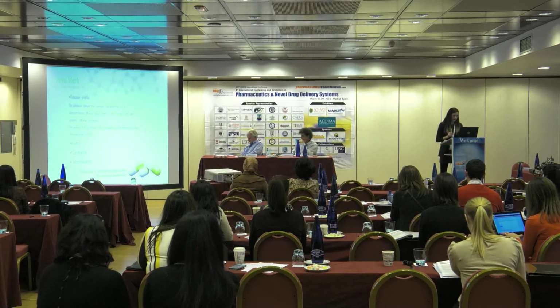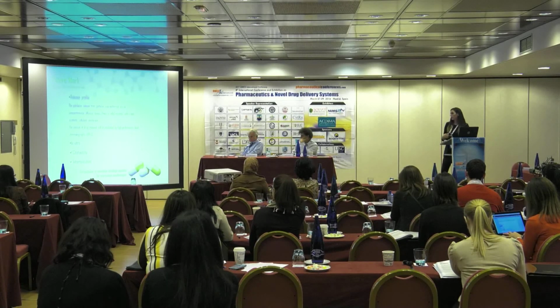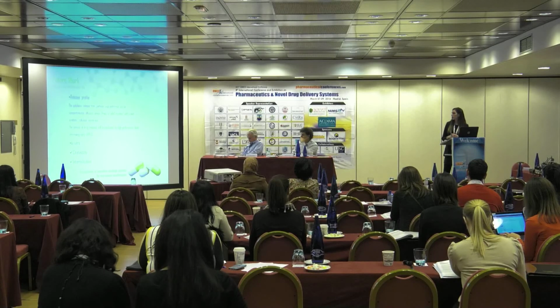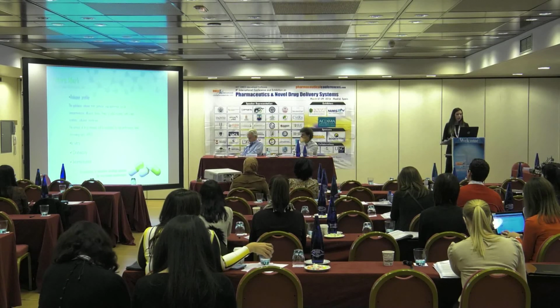As future work regarding this specific system, the polylysine system, involves a release profile, because we have made a release study using a Franz cell, but now we have to quantify all the samples, there are around 300, to check how is the release of the polylysine from this matrix particle. In particular, these peptides that I told you about are considered for a weekly treatment for a specific type of cancers. So our idea is to check if we can get this kind of release profile for this kind of application.